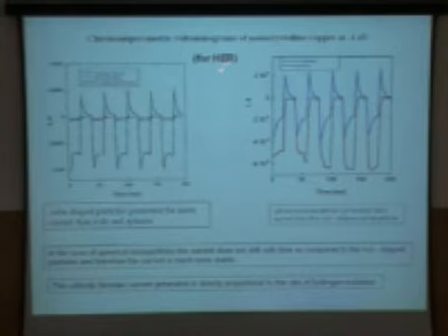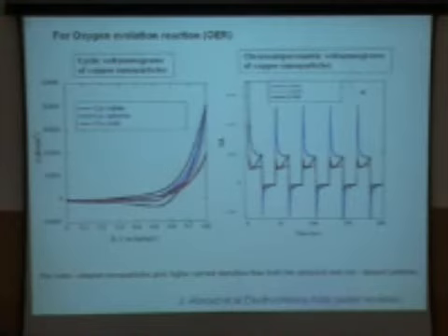So hydrogen evolution reaction. If you look at the black curve, it is very high, and that is for the cube-shaped copper. All of them are copper particles, but the cube-shaped particles show much enhanced activity. You put it in water, so hydrogen will evolve at one electrode, and oxygen will evolve at the other electrode. Both hydrogen and oxygen evolution is the maximum for the cube-shaped particles. That means morphology plays a very important role in the electrocatalysis of water.